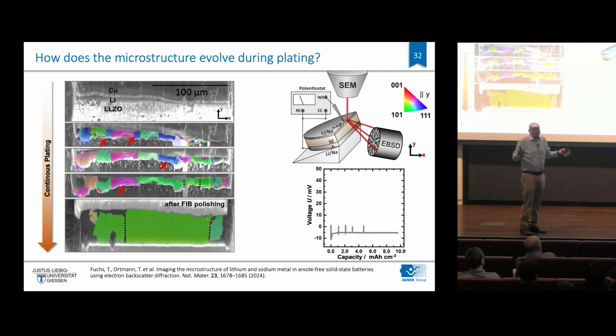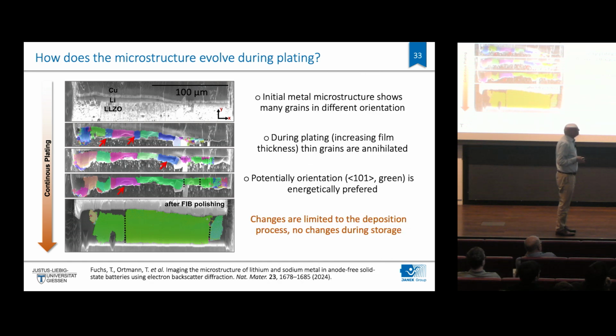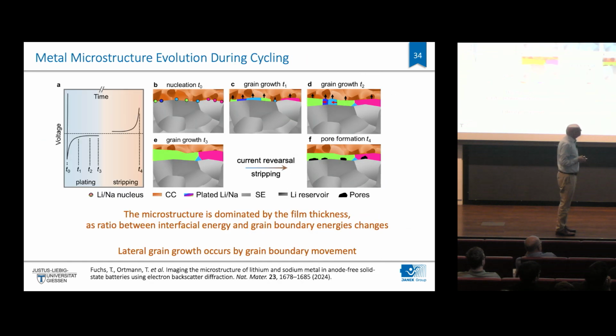And films, of course, always want to grow. Grains want to grow. And that means if there's more grain boundary area, films tend to become more or less single crystalline at the end. And this is, of course, quite exciting. We made a little model for that, saying, okay, there is first nucleation, grain growth, and of course, upon stripping, pores mainly are being created in the grains, not in the grain boundaries, because the grain boundaries are really fast. And that was, at that point, a first point.